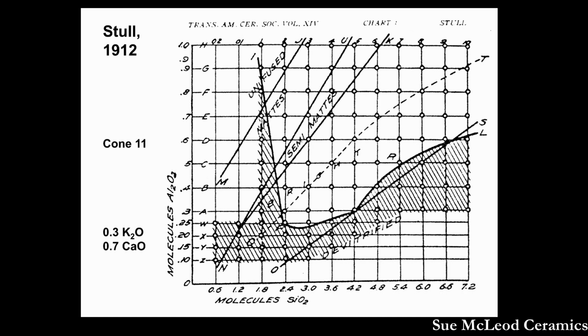Historical and contemporary research have shown that a flux ratio of 0.3 to 0.7 contributes to the highest durability of a glaze. As you can see, this is the flux ratio that Stull used in his research, 0.3 moles of potassium to 0.7 moles of calcium. With a consistent flux ratio, all he did was vary the amounts of silica and alumina to create glazes at all points on the map.